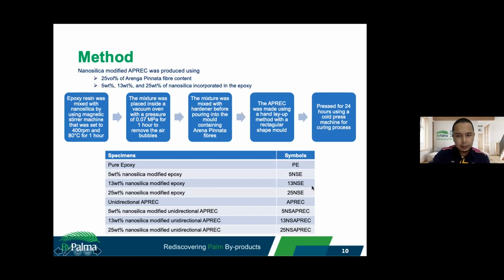So these are the methods used to produce the specimen. First, we use 25 volume fraction of Arenga Pinnata fiber content because this is the optimum volume fraction to get the optimum result for the mechanical properties. And then we have 3 different weight percentages of nanosilica incorporated in the epoxy. So first we mix the epoxy resin with nanosilica by using a magnetic stirrer.